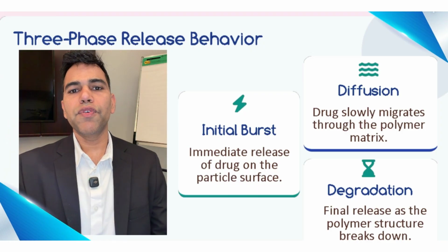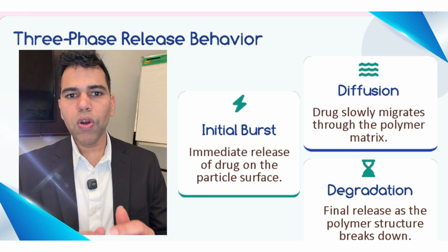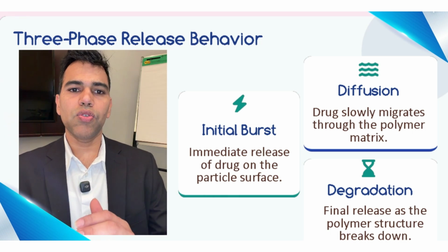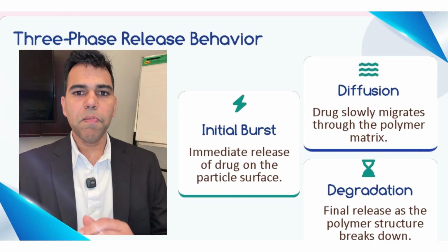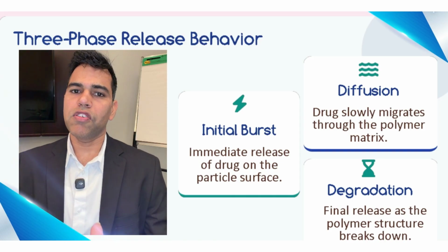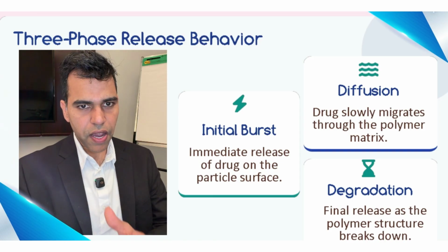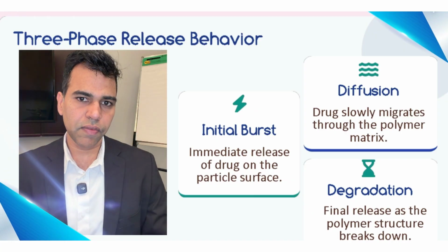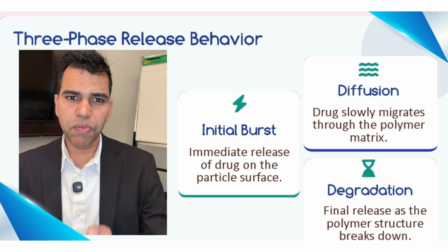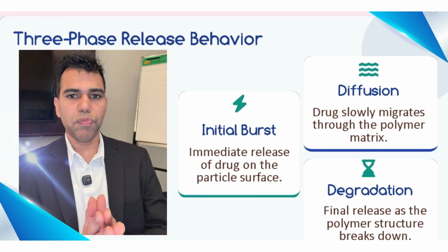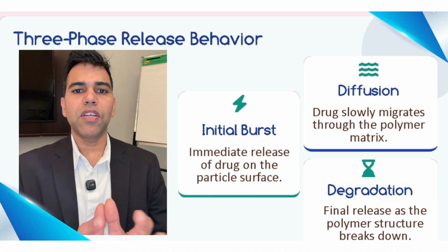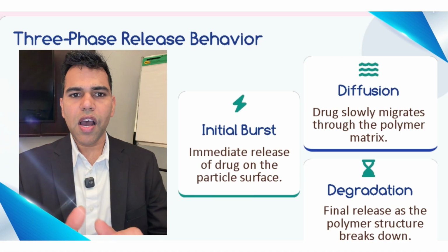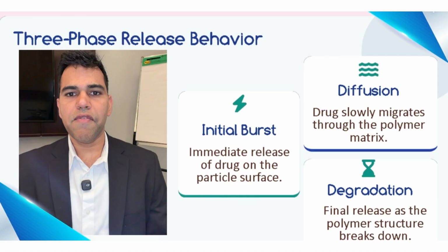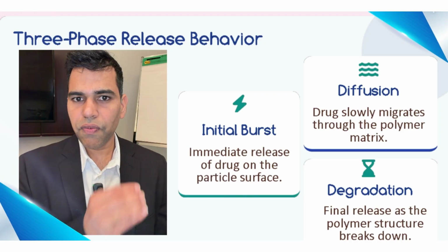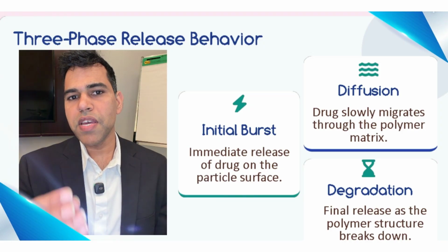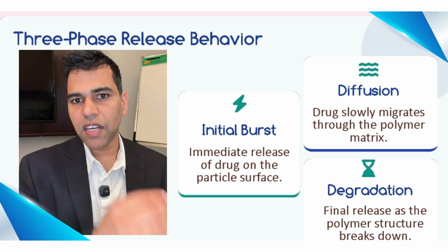Then comes the diffusion phase. The drug slowly migrates through the polymer matrix over days to weeks, maintaining a therapeutic plasma concentration. And finally, the degradation phase. As the PLGA polymer hydrolyzes and its structure breaks down, the remaining drug is liberated. Now ask yourself, if you are a generic developer trying to match this profile, how do you even measure whether you have done it correctly?